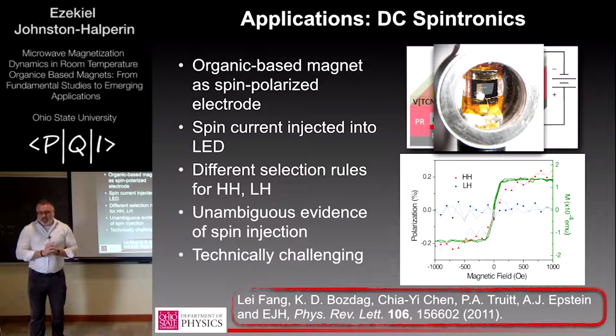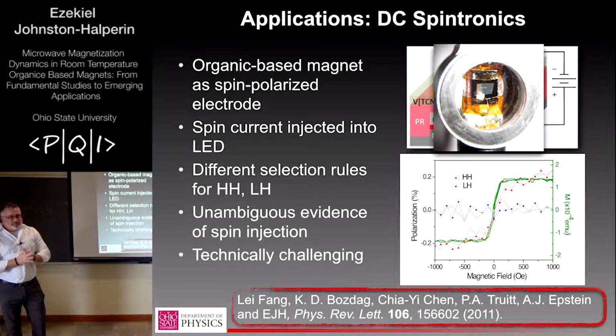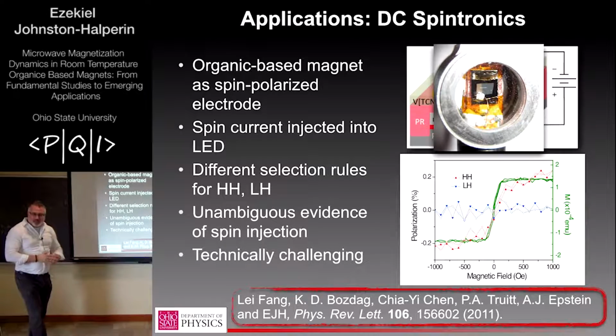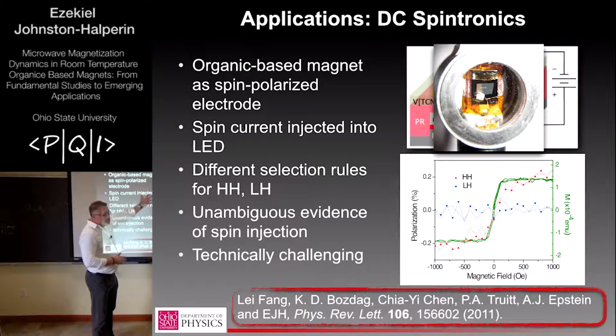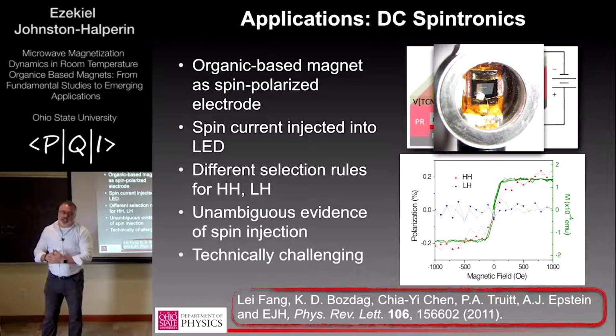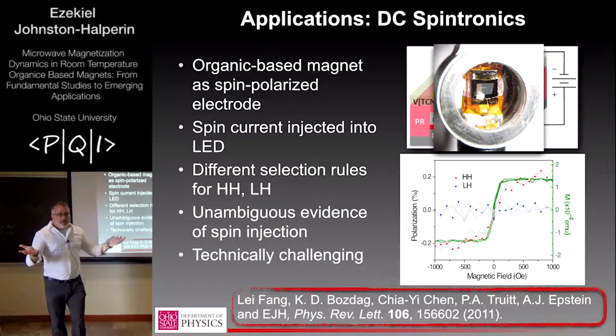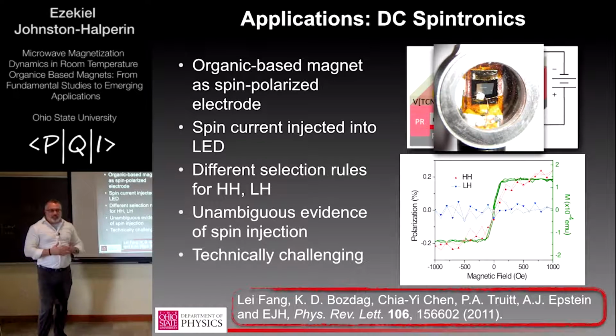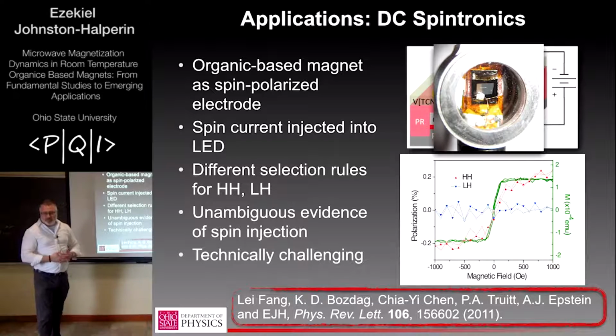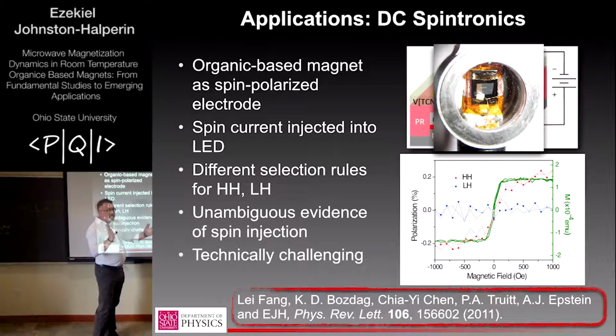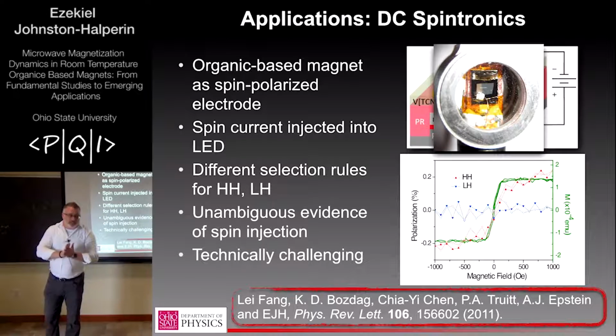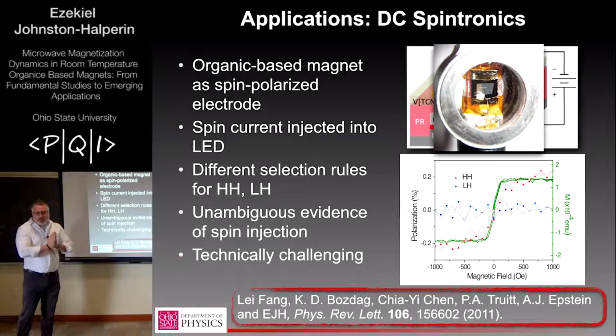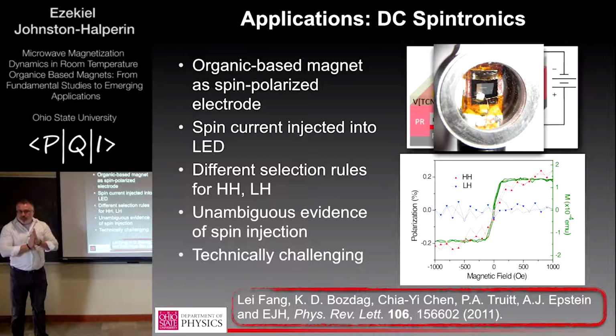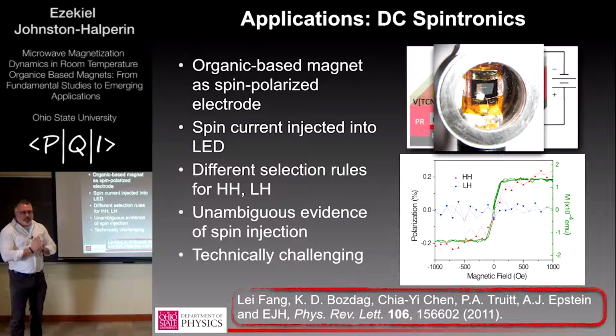You can, with aluminum, which works reasonably well, but aluminum's a conductor, right? So not every experiment works for that. Well, to give away a punchline from a little later in the talk, what we developed more recently is they make epoxies that we pirated from the OLED community that are specifically designed to not react to the organic molecules. And so by coating that with epoxy and then putting a top piece of glass or sapphire on top, we can stabilize it for the weeks to a month under ambient conditions. So this is one of the innovations we've been able to come up with in the last couple of years.